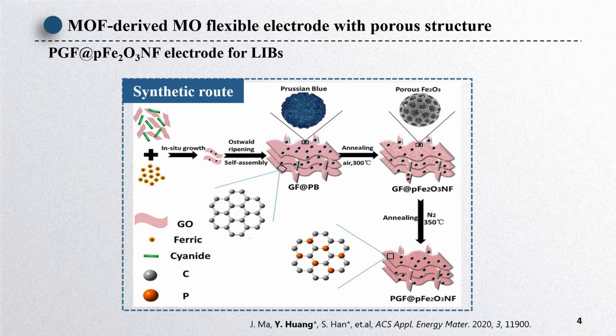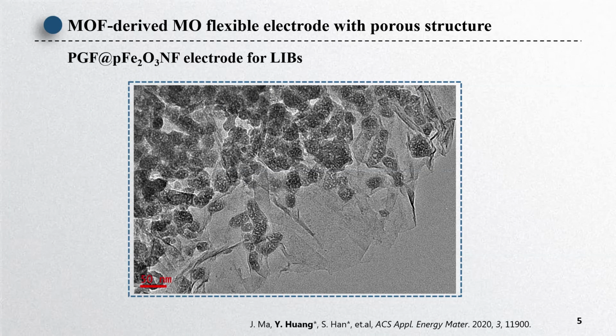After annealing in air at 300 degrees, the PB can be transferred to porous ferric oxide. Then, after annealing in a nitrogen atmosphere at 350 degrees, using sodium dihydrogen phosphate as the phosphorus source, phosphorus can be successfully doped in the graphene. From the TEM, we can find the porous ferric oxide is uniformly distributed on the graphene surface.